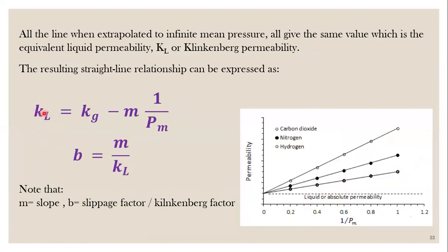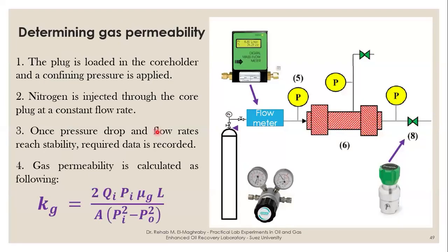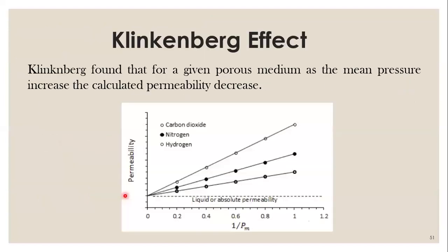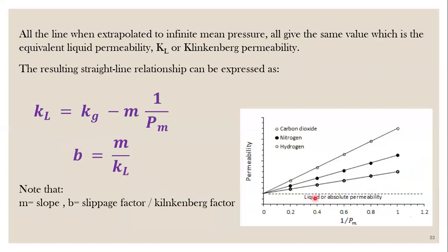So they say there is a relation between the liquid permeability and gas permeability. The liquid permeability equals the gas permeability minus the slope divided by the mean pressure. And the mean pressure is this one plus this one, divided by 2. If you draw the gas permeability on the y-axis, and on the x-axis you draw 1 over the mean pressure, then you will have the slope. So if you have the slope here, and you already have the gas permeability, you can calculate the liquid permeability. And this is what we want.